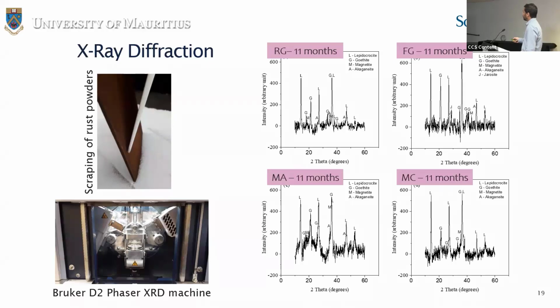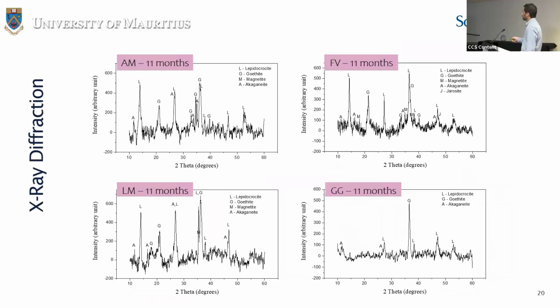After 11 months of exposure at these four sites, we could say the strongest peaks relate to the goethite and lepidocrocite rust phases, and there are low percentages of magnetite, aragonite, and also jarosite rust phase is observed in small amount at FG, which is the site closest to the power station. The four other sites show a similar trend, with the predominant phases being lepidocrocite and goethite.